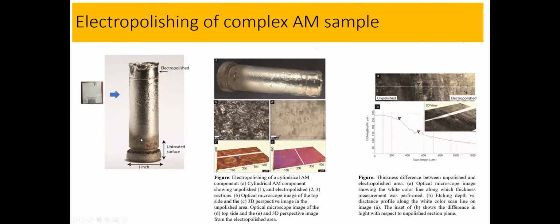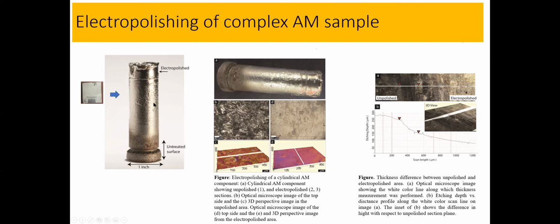As I mentioned in the beginning, we are experts in the field of surface finishing for complex geometry. The cylinder which you are seeing here is made of stainless steel, and it is a hollow cylinder, and hollow means it has a spiral inside. We started working on this solution, how to clean inside and outside. What I'm showing here, from the bottom, used to be the starting surface roughness. But you can make it to almost atomically, not atomically, but nanometer scale smoothness.